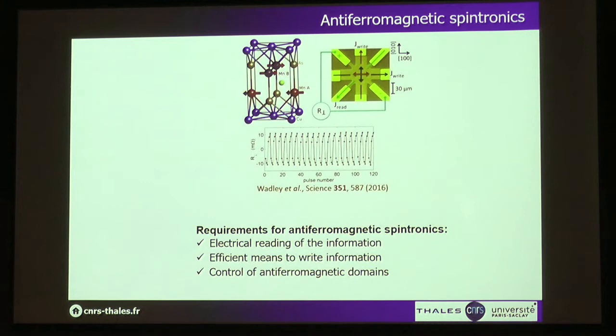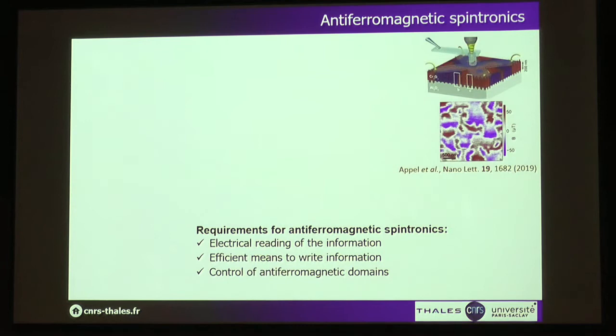This is not so simple because researchers realized that when they tried to look at the anti-ferromagnetic domains in these films, it is actually very complicated. When applying current, they are switching only a minor fraction of the domains. So we would need a way to deterministically control the anti-ferromagnetic domains with electrical input. To be able to control these domains, we need to be able to see them, which is very challenging because we cannot use conventional techniques such as magnetic force microscopy. But recently, there were results from NV magnetometry experiments where anti-ferromagnetic domains could be imaged.